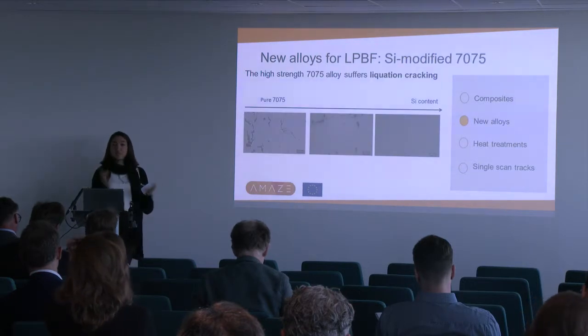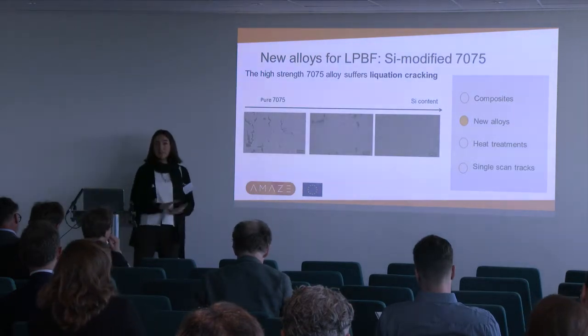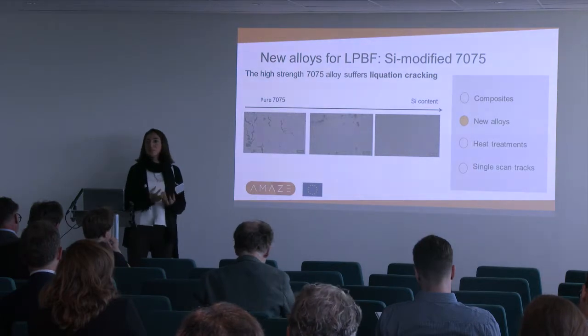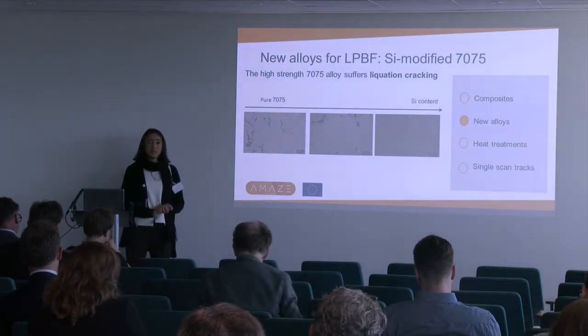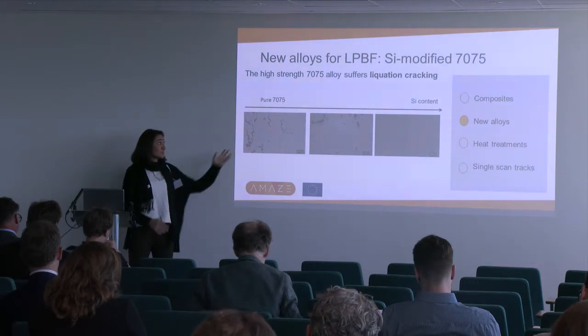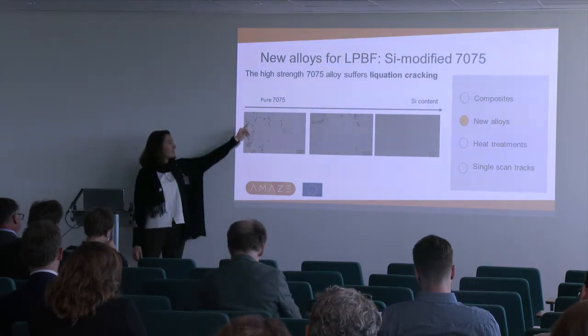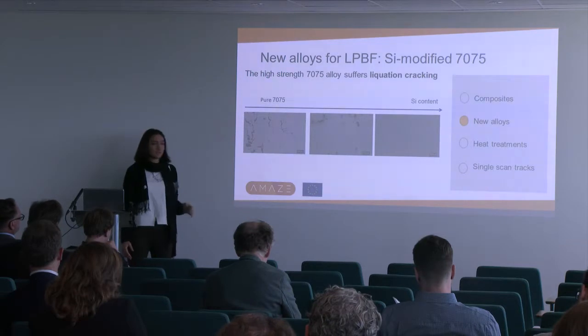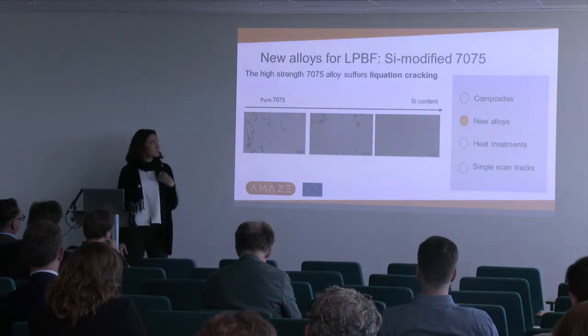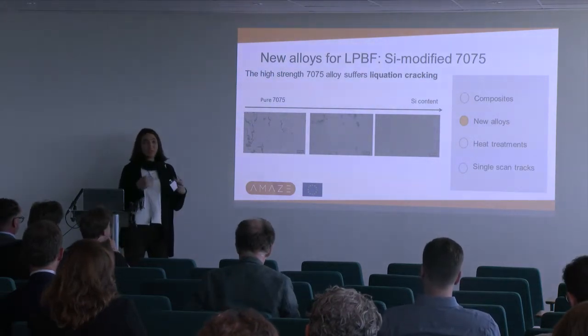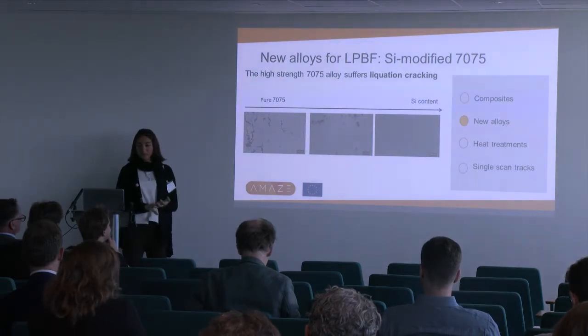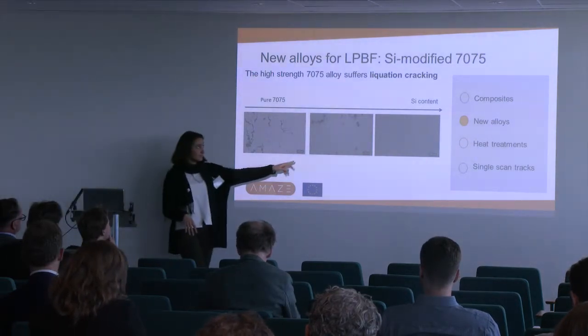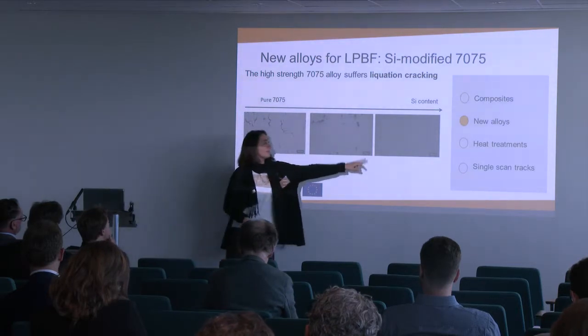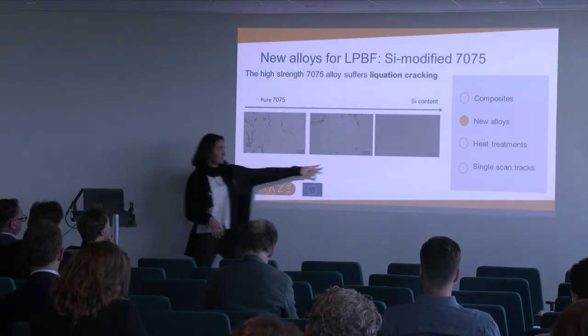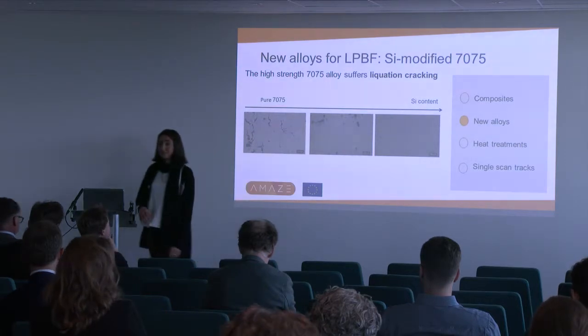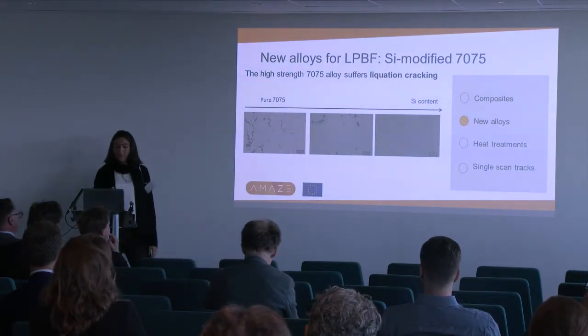Okay, so then I will move to the other alloy composition, which is the 7075, which we changed in order to be processable by powder bed AM. So, as I said, the pure 7075 strongly cracks. So we can find all these cracks along the building direction. And this is mainly due to the large solidification range of the alloy and the low fluidity of the alloy in the molten state. So we started adding silicon, and here we have some silicon more, and here this was the composition that allowed us to have crack-free samples.